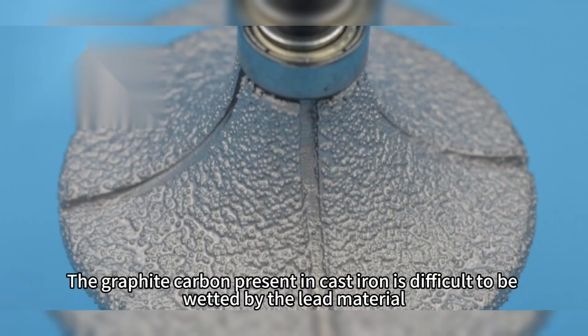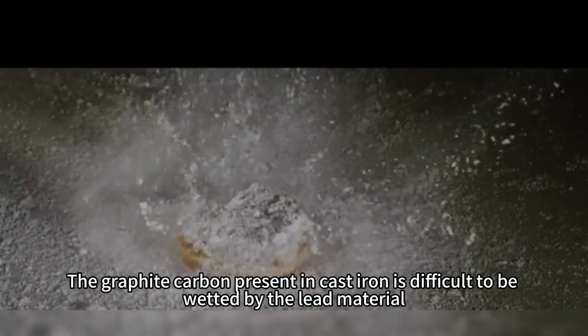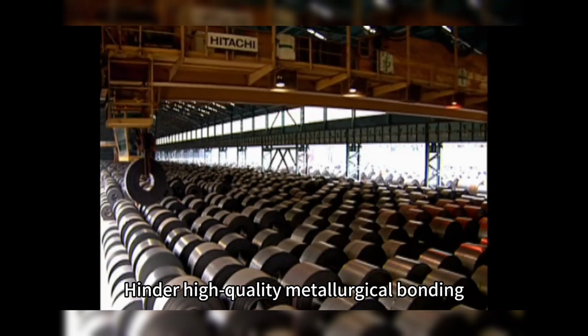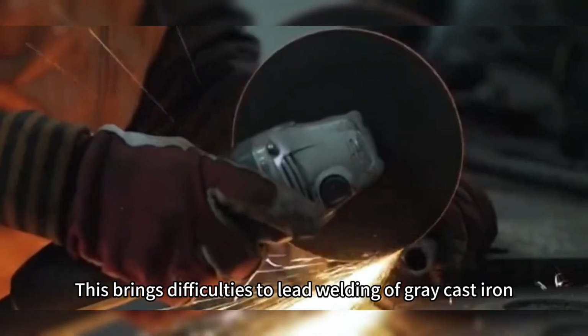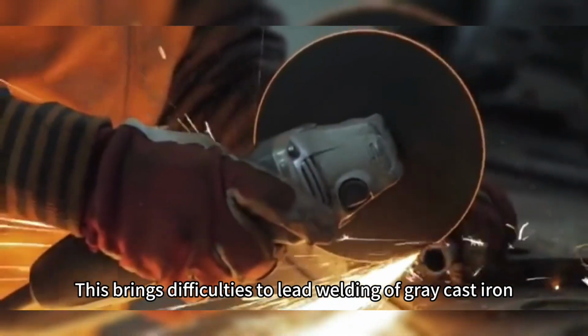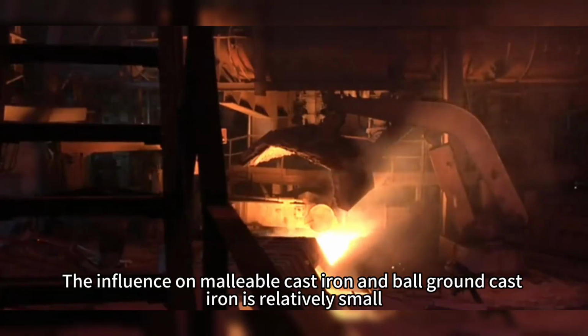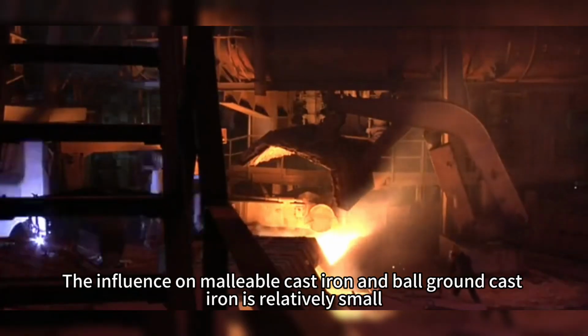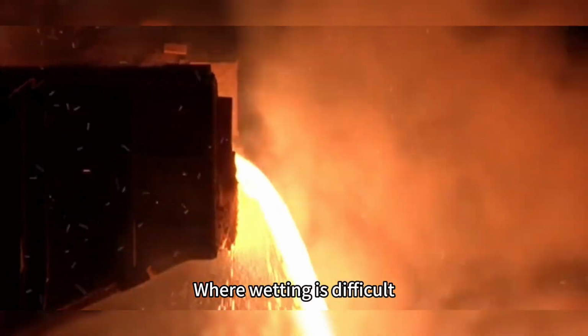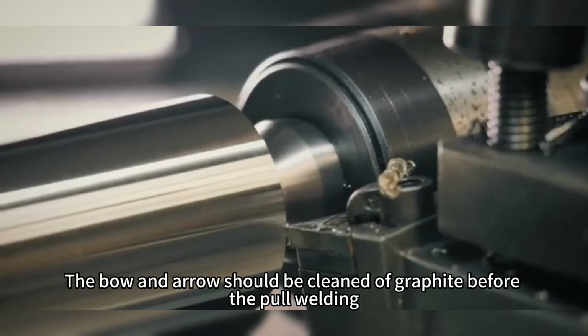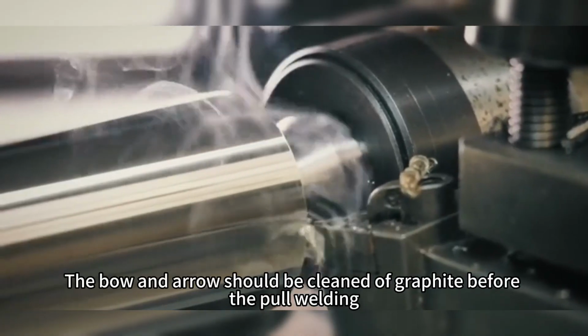The graphite carbon present in cast iron is difficult to wet with the filler material, which hinders high-quality metallurgical bonding. This brings difficulties to braze welding of gray cast iron. The influence on malleable cast iron and ductile cast iron is relatively small, though welding is still difficult. The ball and flake graphite should be cleaned before the braze welding.